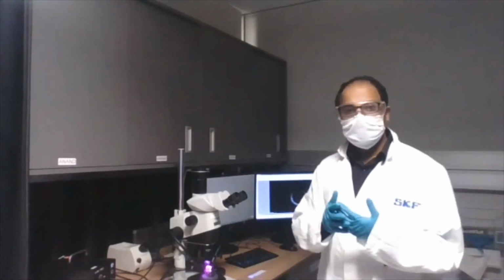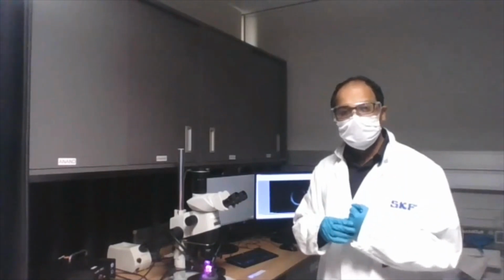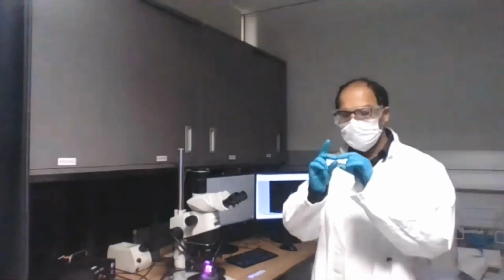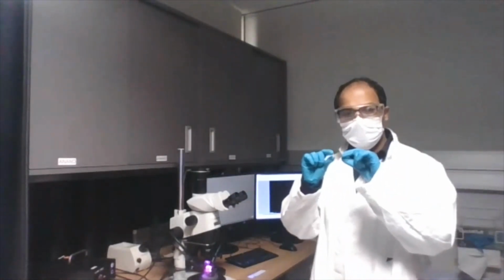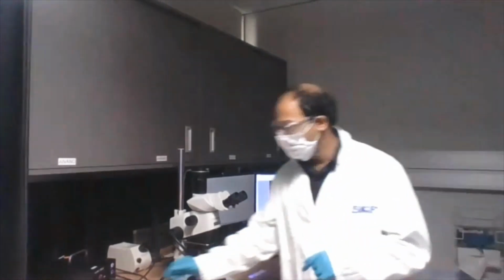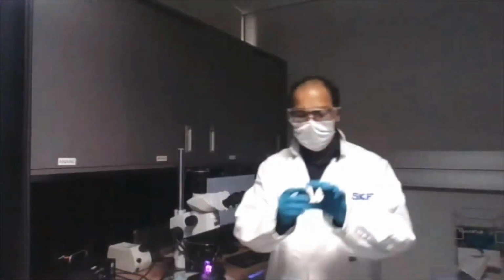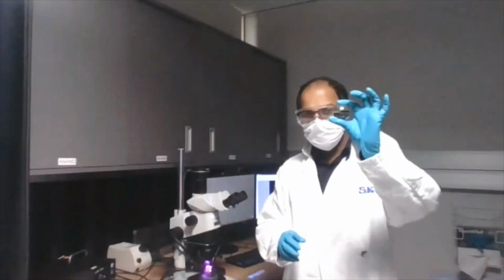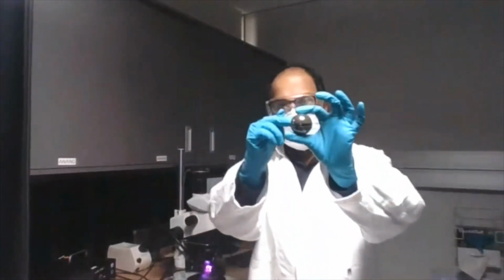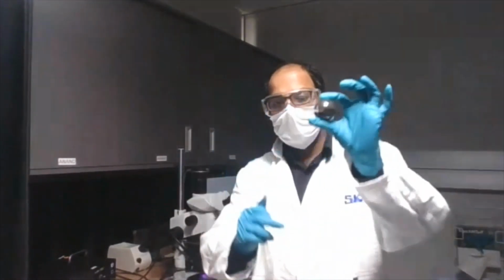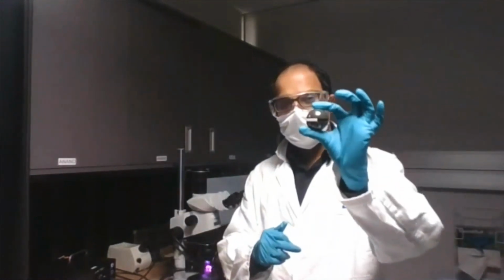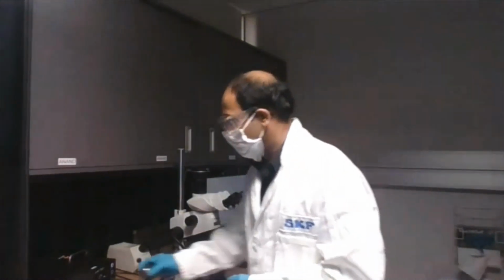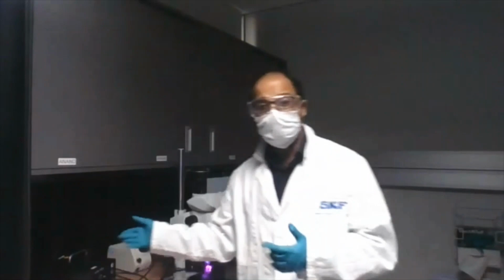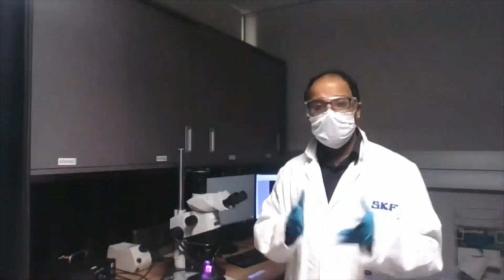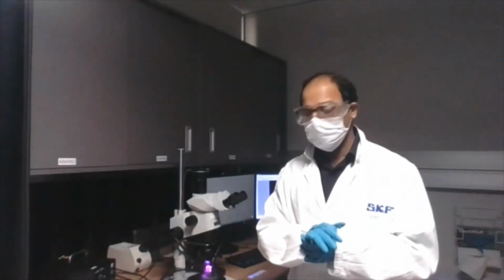There are several methods, but here I will only discuss the strength method. Generally, they use a small ceramic bar to get the strength of the materials. However, in SKF, we have developed a unique test called the notch ball test, wherein we make a notch directly on the ceramic rolling element and we test them in compression to get the strength of this material. SKF has driven the ISO for this kind of notch ball test. It's actually one of the first industries to use it.